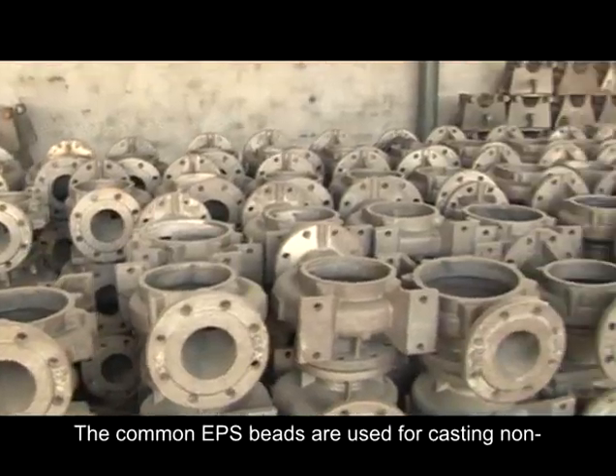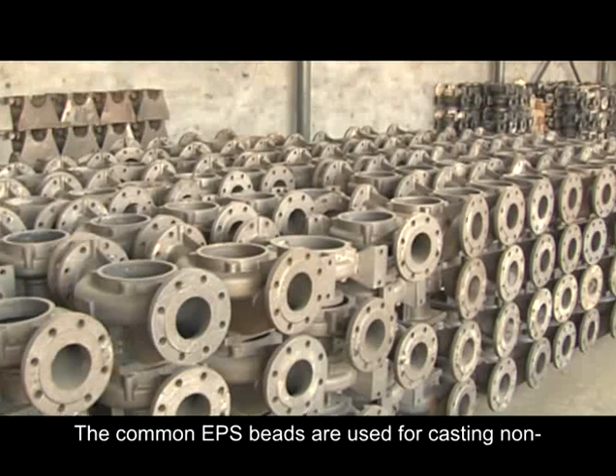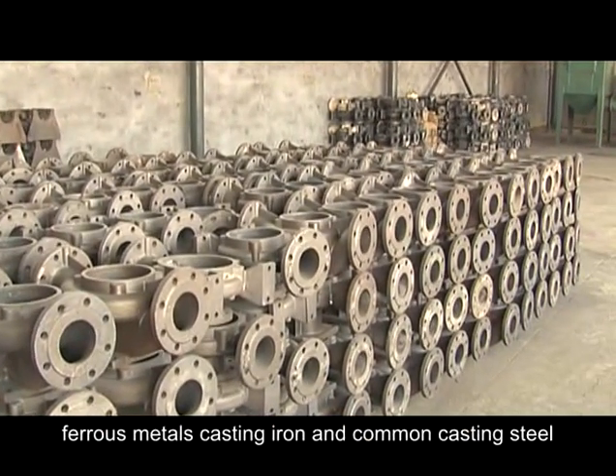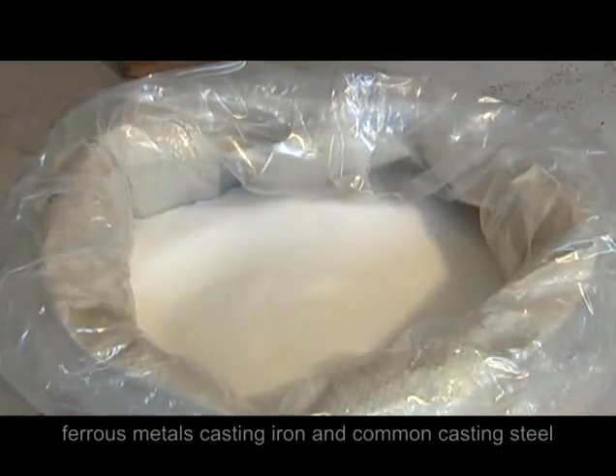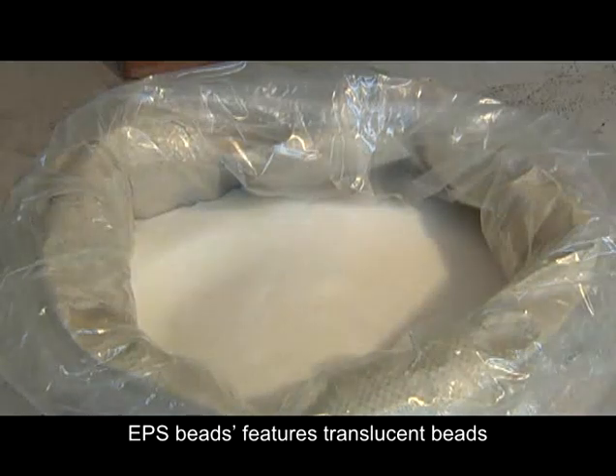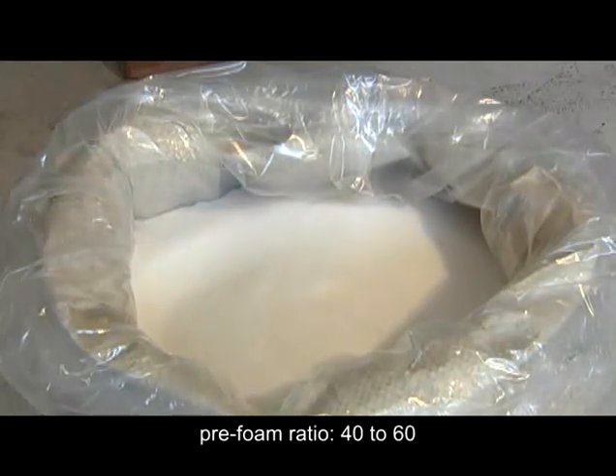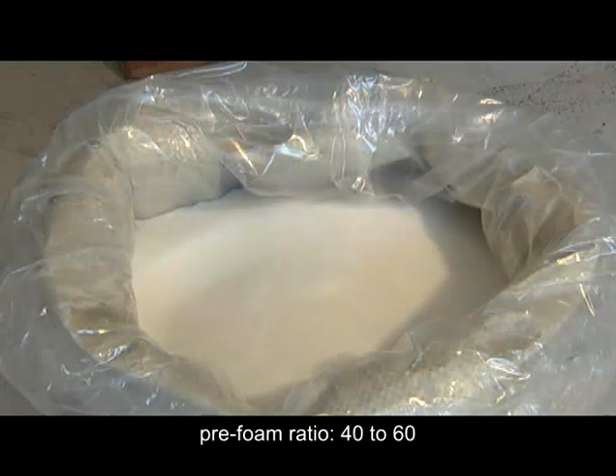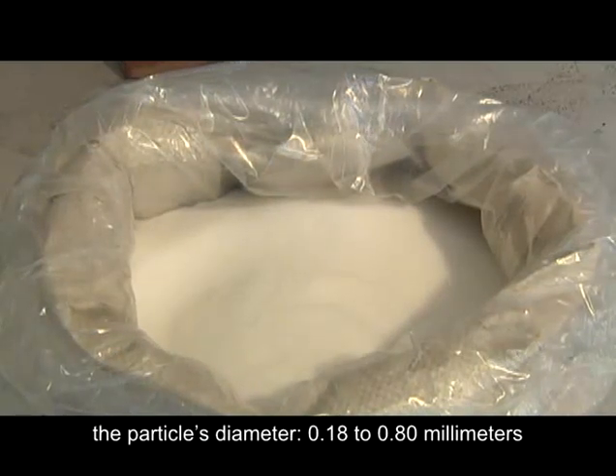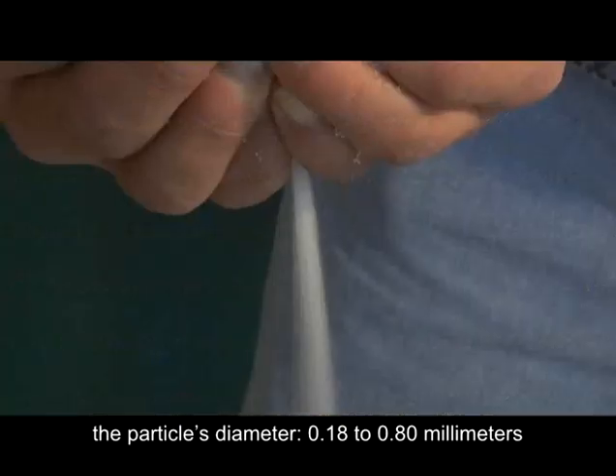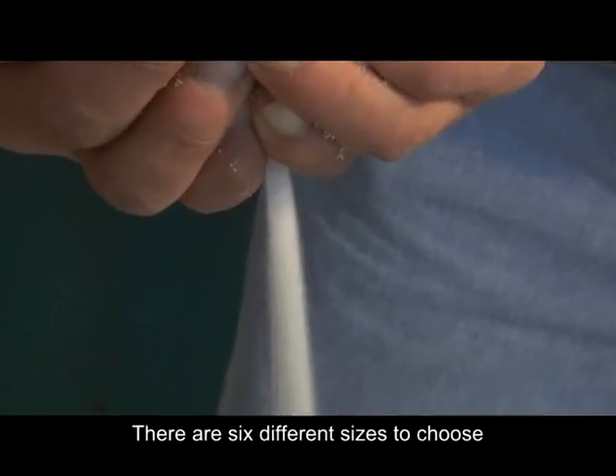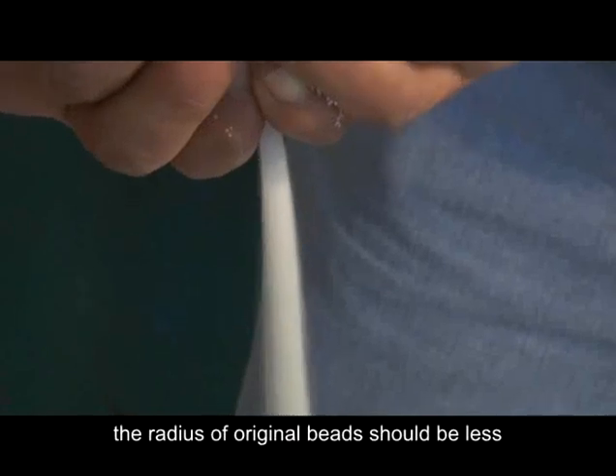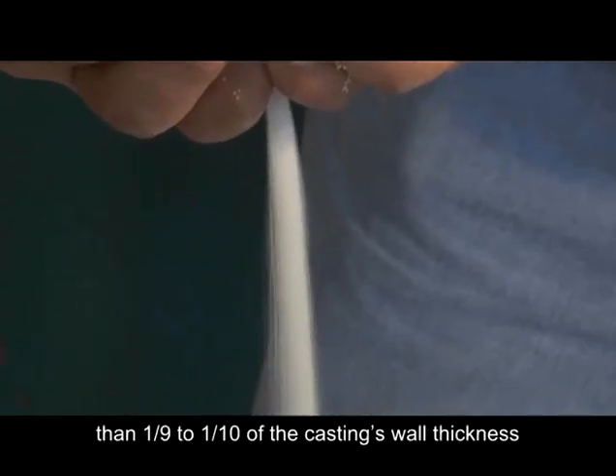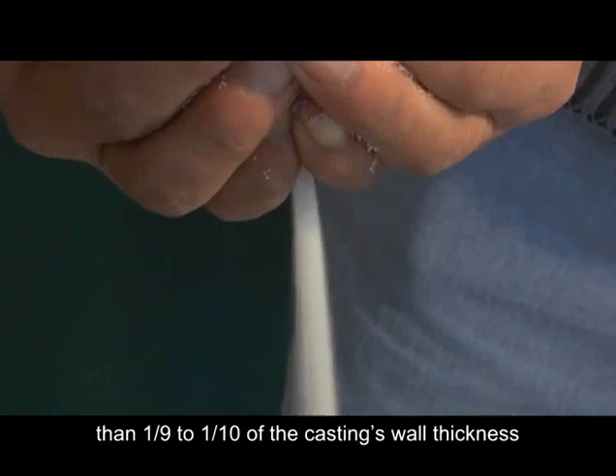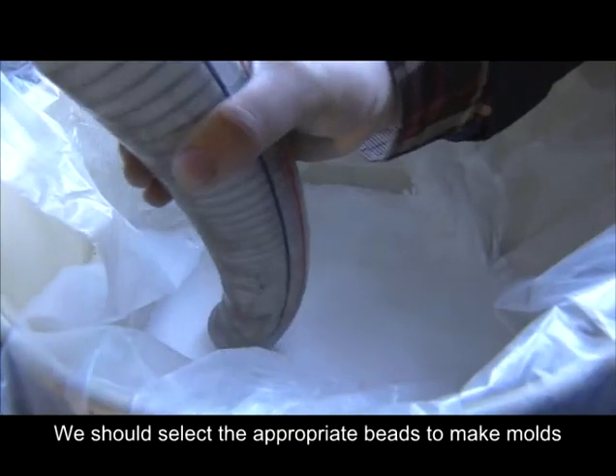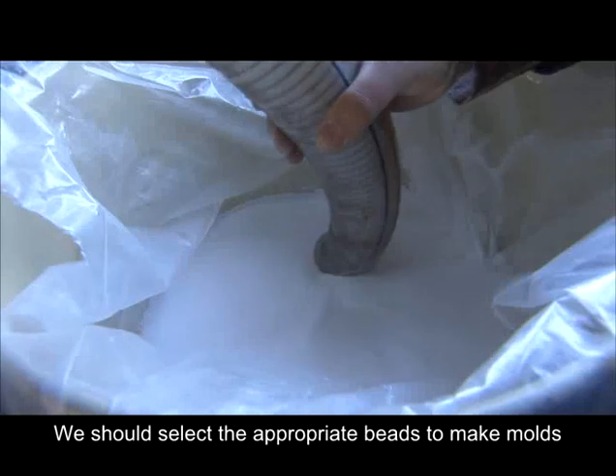The commonly used EPS beads are used for casting non-ferrous metals, cast iron and common cast steel. EPS beads feature translucent beads, pre-foam ratio 40:60, and particle diameter 0.18 to 0.80 millimeters. There are 6 different sizes to choose from. The radius of the original beads should be less than 1/9 to 1/10 of the casting's wall thickness. We should select the appropriate bead to make molds.